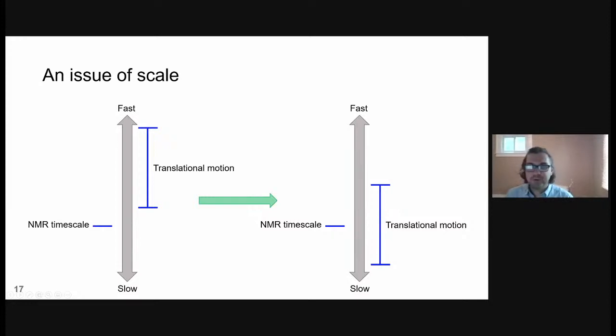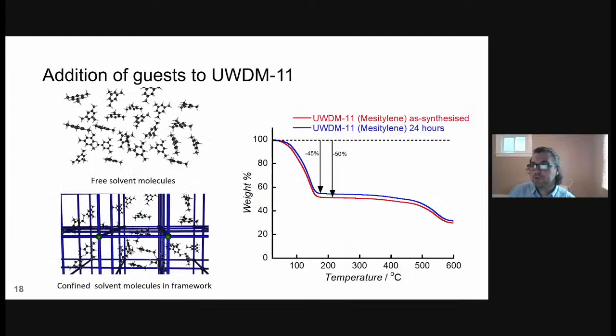There are a number of ways that you can change the rate of translational motion in these rotaxane type systems, most of which involve going away and doing some more organic chemistry and modifying either the ring or the axle. However, since we're working with MOFs, we decided to use a different approach. We instead decided to introduce guest molecules into the cavity of the MOF to see if we could increase the effective viscosity of the microenvironment that this rotaxane is experiencing, and see if that would slow down the translational motion.